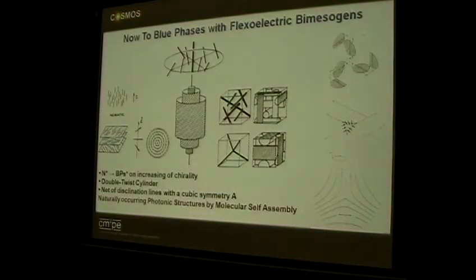Blue phases, funny things. Blue phases are a peculiar phase that form in tightly twisted chiral nematics and tightly twisted smectics. I think Ken asked me, why do you get blue phases before you get the chiral nematic? And the answer is you've got a highly twisted structure, which is trying to form a chiral nematic phase, but because you've got little local regions of high twist, they co-align with each other and form the so-called blue phases. But because of that, because it was almost an intermediate step, the temperature width of the blue phases was very, very narrow. 1 or 2 degrees was typical.